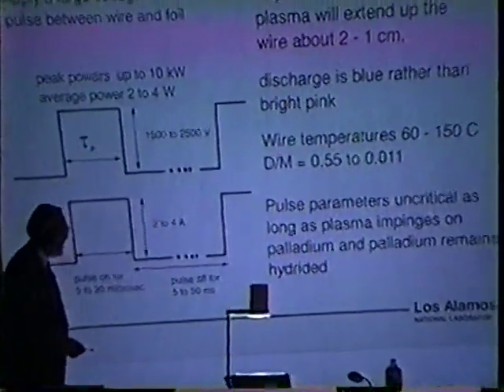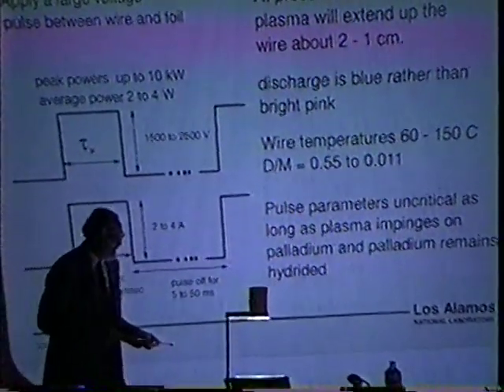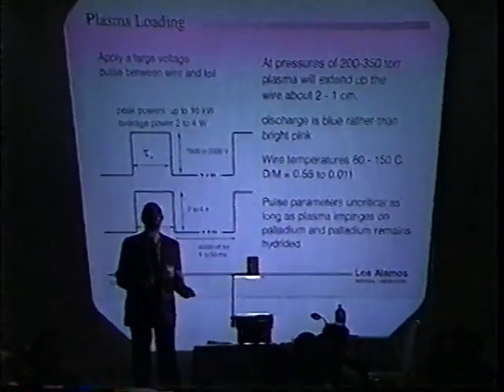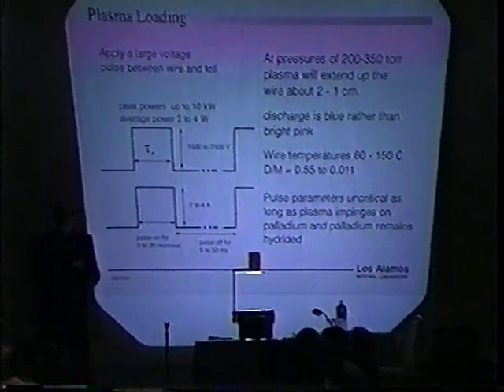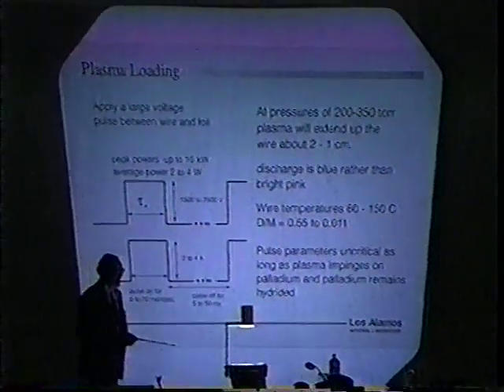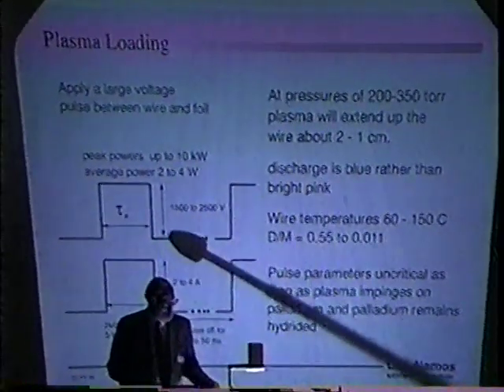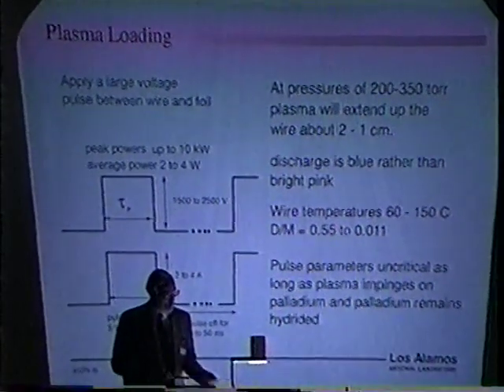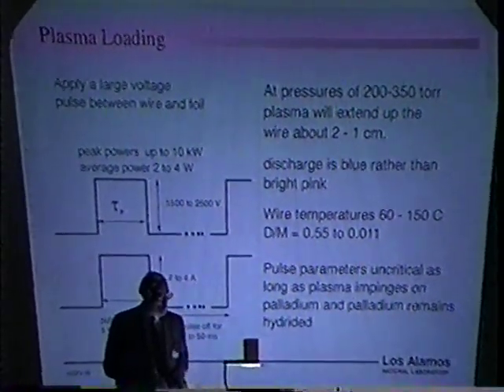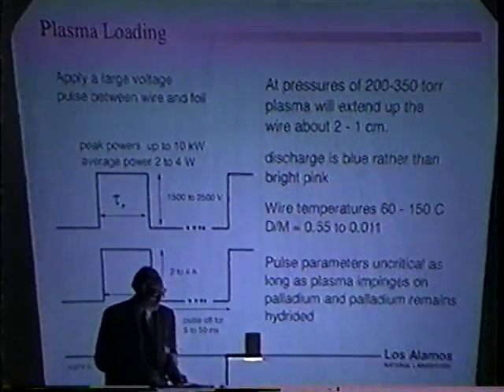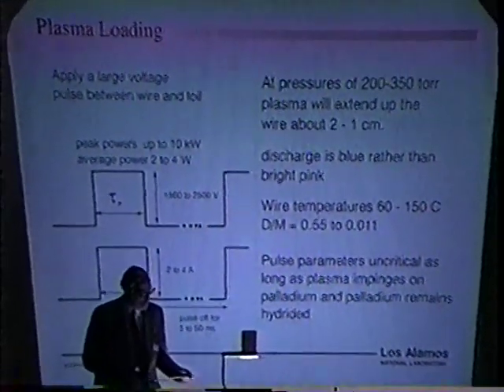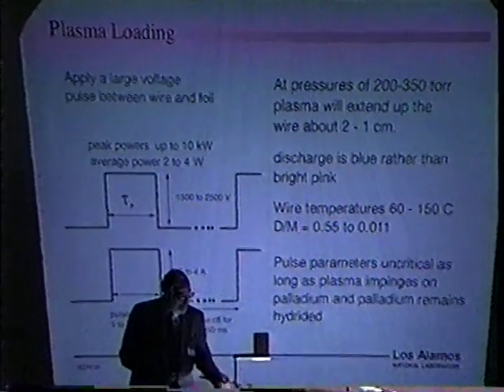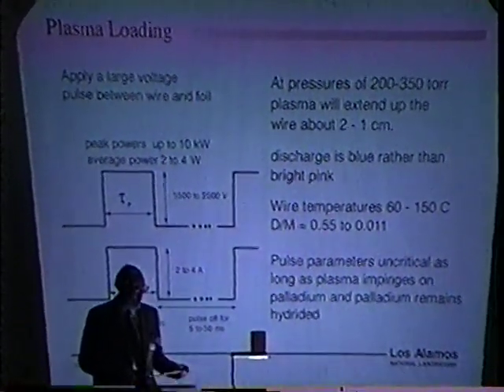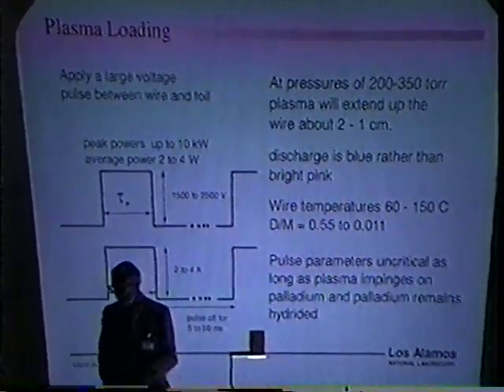This shows the conditions in the cell, and you can see there's a pulse. This is an ideal pulse, I might add. There's a lot of ringing, and it's very messy, but this is the ideal way it looks. So he puts 1,500 to 2,500 volts on it, 2 to 4 amperes of current over a short period of time, 5 to 50 microseconds or milliseconds. And this causes a discharge, and it's during that discharge that the tritium is produced.